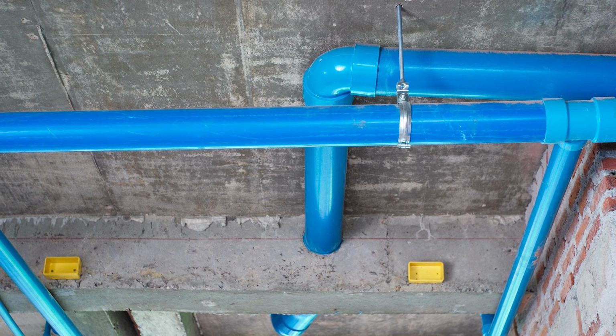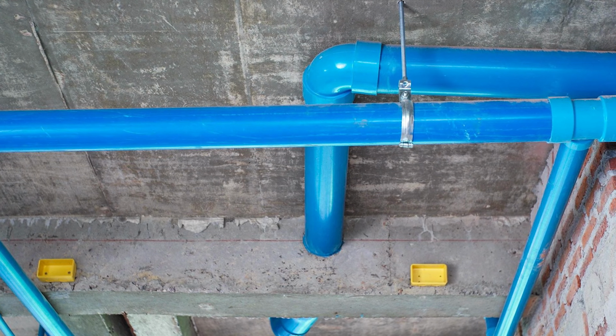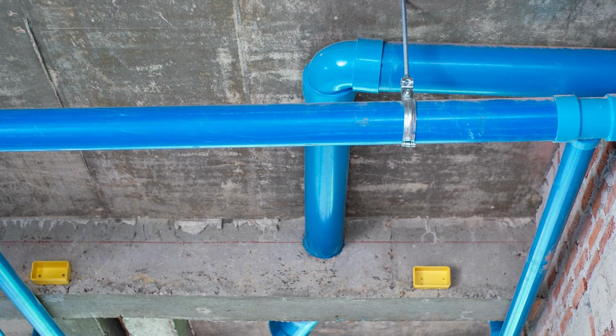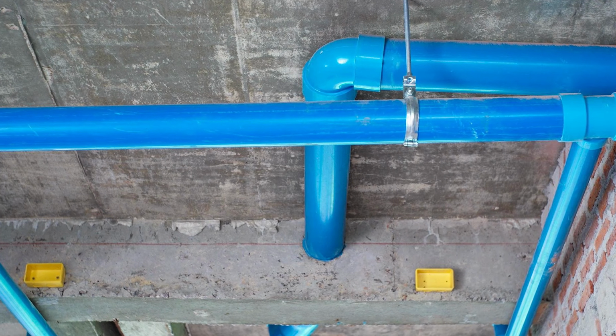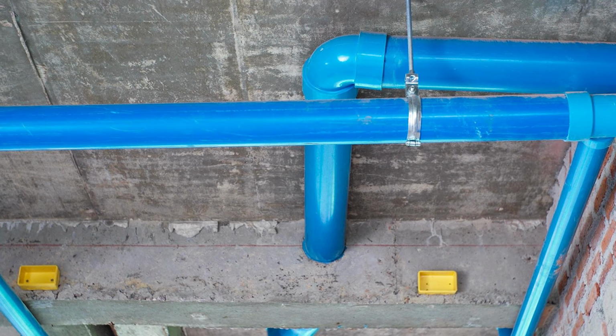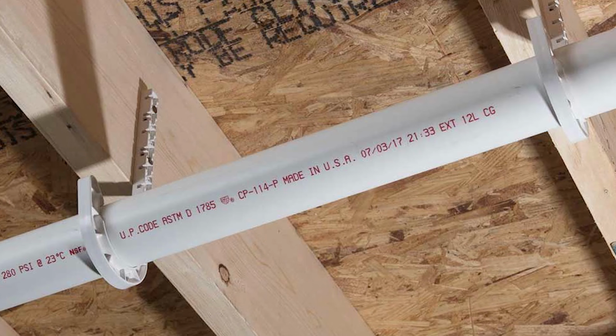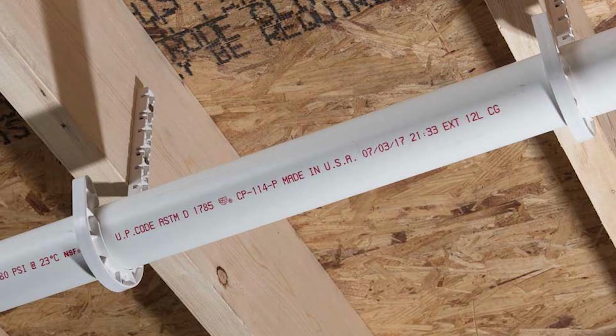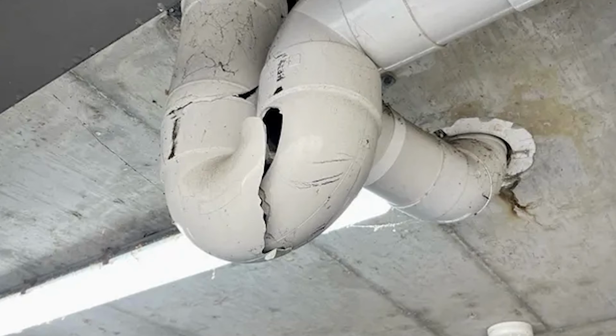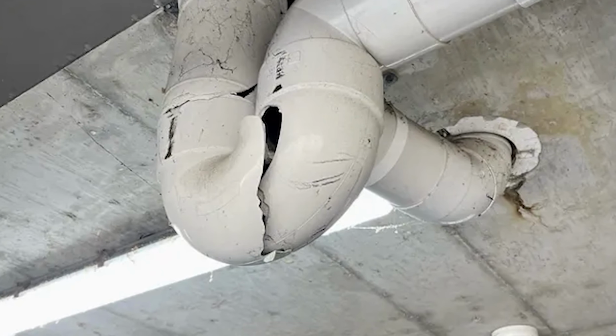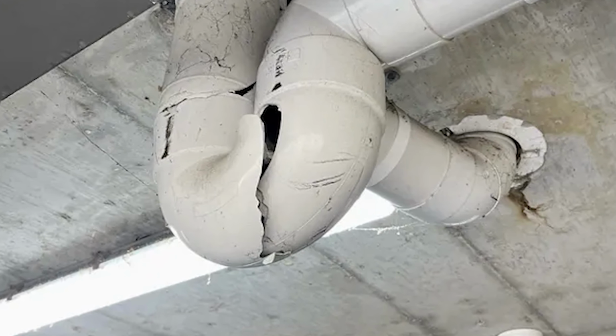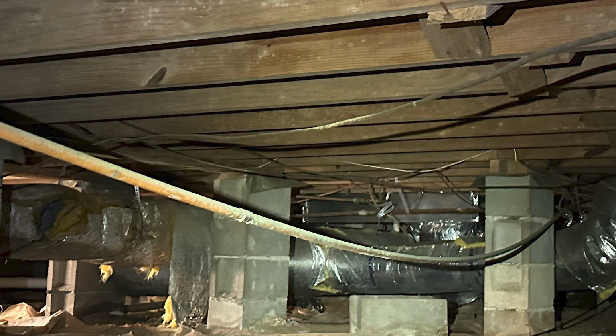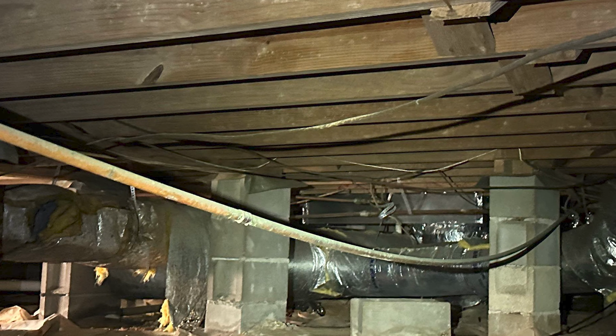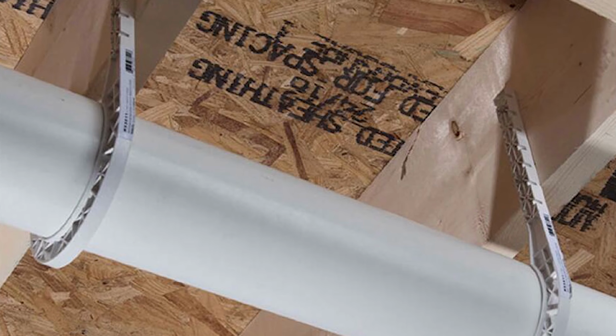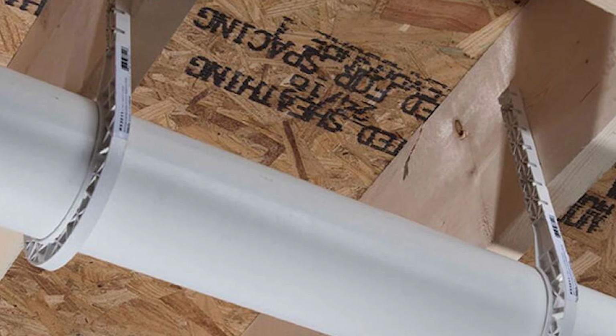Over months and years, that constant movement works against every fixed connection in the run. When PVC has nowhere to move, the stress concentrates at fittings, at glued joints, and at any point where the pipe passes through a drilled hole or hanger. Joints open up. In worst cases, long horizontal runs will bow and buckle in ways that cause real structural damage. The solution is to plan for movement before you install.